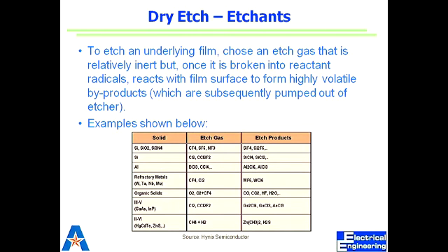Somebody may ask, okay, in dry etching, SiF2 is formed and it resides on the surface. How do you remove it? Okay, so it's not removed. You don't need to wash it or do something like that. It's automatically removed because SiF2 is converted to SiF4 when it is reacted with more fluorine. We'll discuss that later on as well.